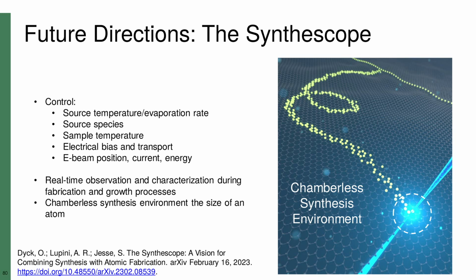We can view e-beam-induced deposition as a special case of this process. The global parameters are set by introducing a molecular precursor gas at a particular partial pressure, but nothing happens until the chamberless synthesis environment is created by e-beam exposure. The conditions for spontaneous material transformation are not globally available. In the STEM, this concept can be scaled down to a single atom, provided that we let go of the specific reaction used in e-beam-induced deposition and speak more generally about a chamberless synthesis environment.